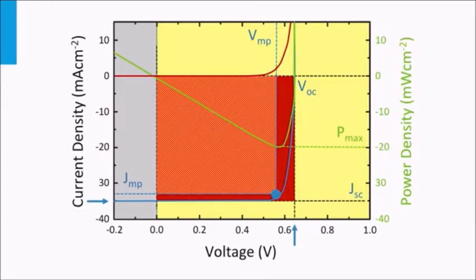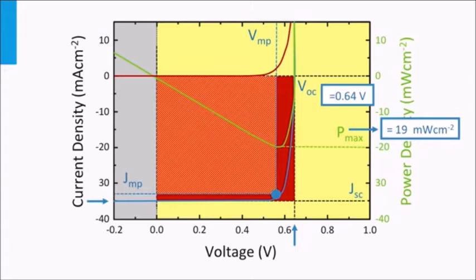Let's get a feeling of typical values. Let's look at this example of a JV curve and assume that it has been measured under standard test conditions. The JV curve represents a typical value for crystalline silicon-based solar cells. The maximum power density is 19 milliwatts per square centimeter, which means under standard irradiance of 100 milliwatts per square centimeter, the conversion efficiency is 19%. If we consider the open circuit voltage of 0.64 volts and the short circuit current density of 35 milliamps per square centimeter, we arrive at a fill factor of 84.8%.